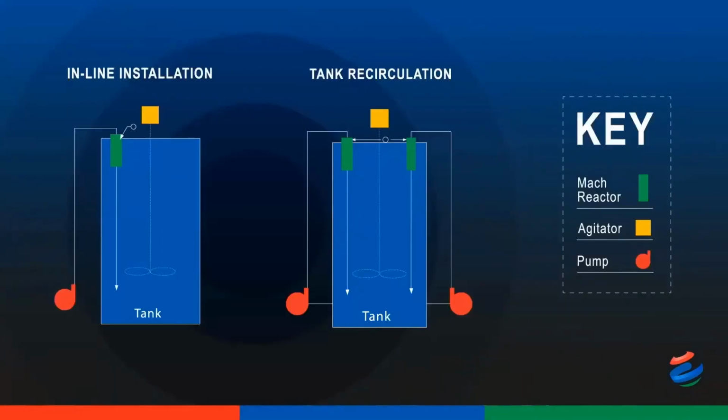So onto the practical aspects of how to implement and install the Mach reactor technology on your plant. We would typically run the Mach reactor on recirculation on a leach tank without carbon. This tank may or may not have cyanide, depending on whether it's a pre-oxidation or boosted leach application. Where we may have the luxury of a second leach tank available to us, and provided that there is no preg robbing, then we may also run the Mach with cyanide on this tank for a boosted leach ahead of carbon adsorption.